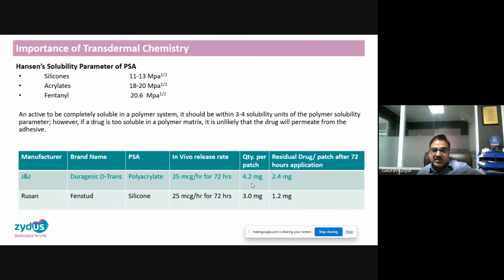of the drug. But if we use silicones, which is my research project, Rusan, where the problem of solubility is less, therefore I use a mixture of silicones, and we have reduced the quantity per patch from 4.2 milligram to 3.0 milligram to get the same in vivo drug release profile.